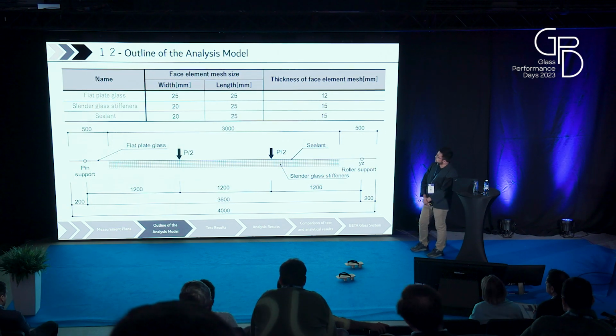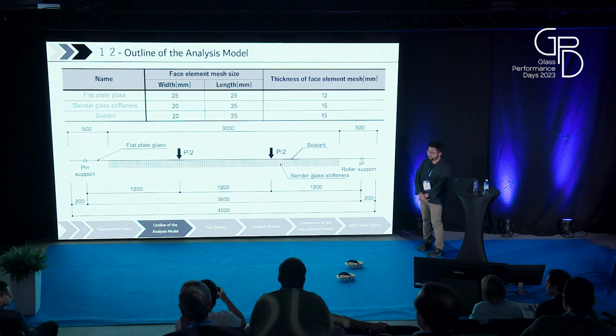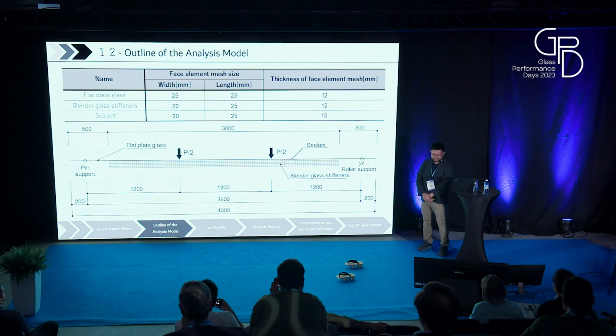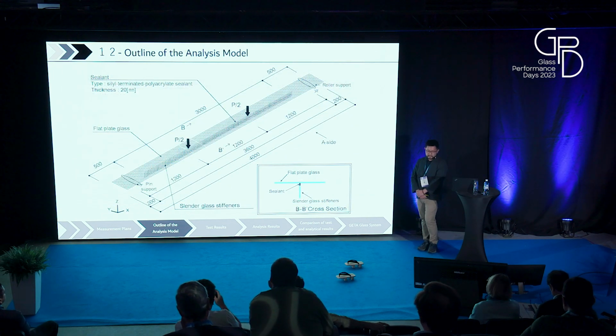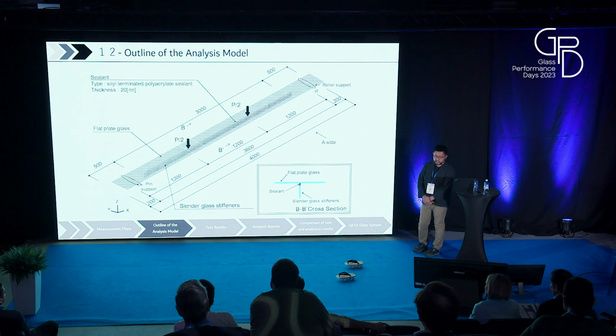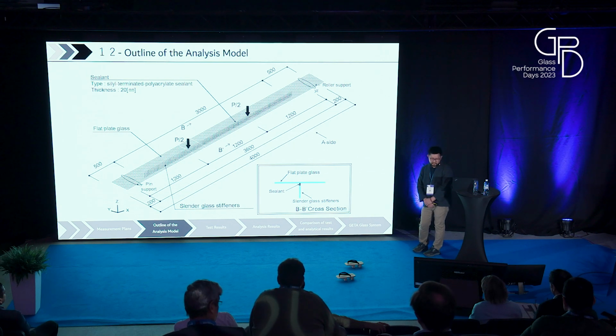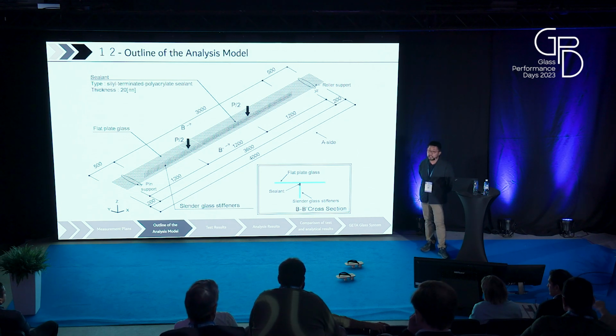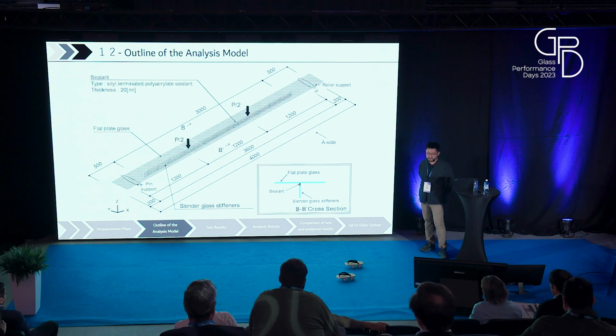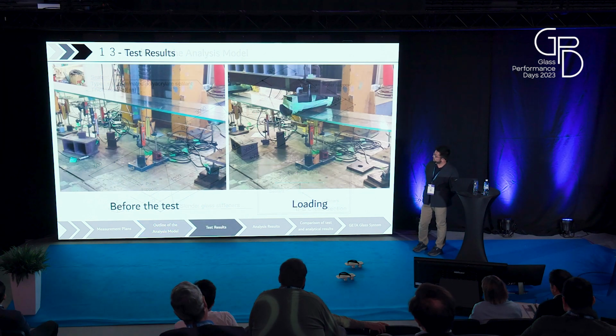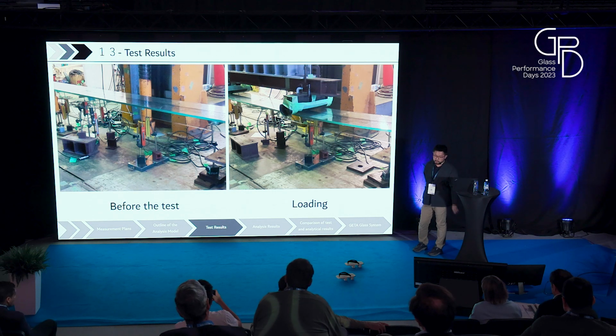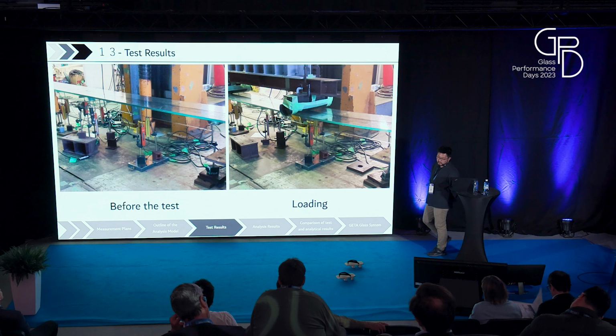Here's the overview of the analytical model. For the loading of this analysis, an elastic analysis is performed by setting up a concentrated load at the force points. The force is applied at the points where the distance is divided into 3 equal sections, which is 1,200 millimeters from both supporting points. And this is how the test specimen was deformed, from the left, which was before, to like this.